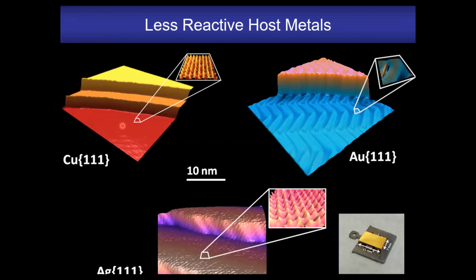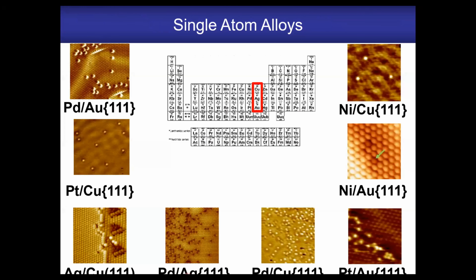So we start the experiments with our host metal surfaces. Typically we use copper or gold or silver, which are more inert, weaker binding metals that typically exhibit high selectivities but low activities in the reactions they catalyze. And then we look at the periodic table and we look to the left of those elements and we find more reactive dopant atoms we can alloy into the surfaces. So palladium, platinum, nickel, we're now onto rhodium. And what we find in some cases, like palladium gold, platinum copper, palladium silver, nickel gold, is that we get this nice atomic dispersion of just single atoms substituted into the host surface.